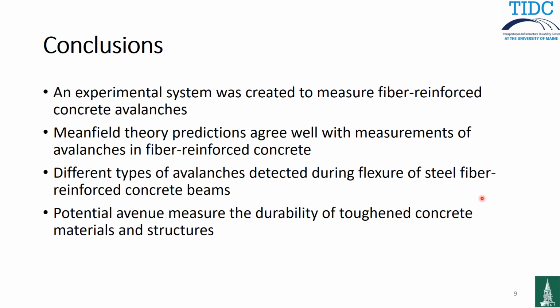Conclusions here. An experimental system was created to measure the fiber reinforced concrete avalanches. We should mention here that acoustic emission can be another method to study avalanches, but neither this high stress-time method nor the acoustic emission method has been reported before to study the avalanches of fiber reinforced concrete materials. Second, the mean field theory prediction agrees well with the measurement for the avalanches in fiber reinforced concrete, and we found different types of avalanche during the fracture behavior.